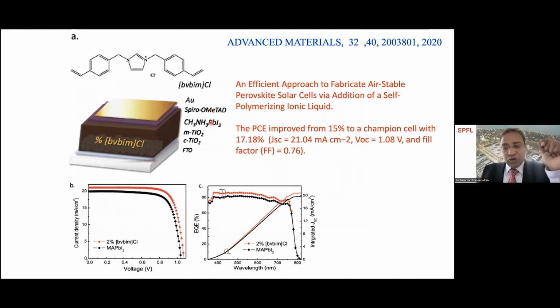The purpose I will show you here again. If we take all our perovskite solar cells, we are fabricating solar cells under nitrogen atmosphere in glovebox conditions. So can we make these perovskite solar cells outside? The reason why we are doing this is this ionic liquid can self-polymerize at heating at 80 to 90 degrees temperature. Since we are heating our perovskite solar cells at this temperature, this can polymerize.